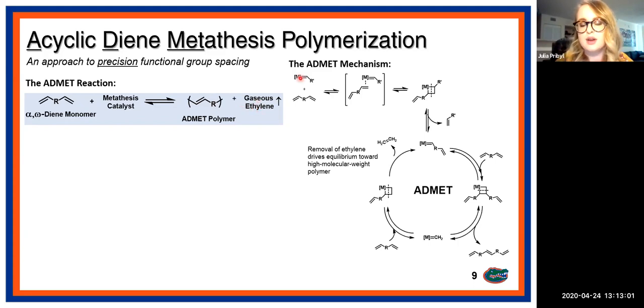So the way that this works, I'm gonna direct your attention to the mechanism. We start with a transition metal coordinated to a benzylidene or an alkylidene species. And the way that it enters the catalytic mechanism is it first coordinates a monomer, in this case an alpha omega diene monomer, forming the metallocyclobutane intermediate. And then once this alkylidene ligand leaves, it enters the catalytic cycle. So then at this point, another molecule of monomer can coordinate to form another metallocyclobutane ring. And then at this point, we generate a dimer. And then our metal catalyst is coordinated to a methylene group. And then finally, after one more coordination of monomer, we get scission of a molecule of ethylene, which leaves,